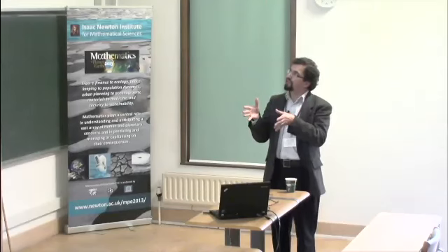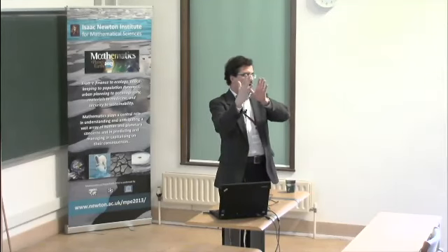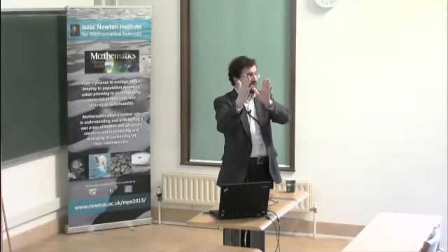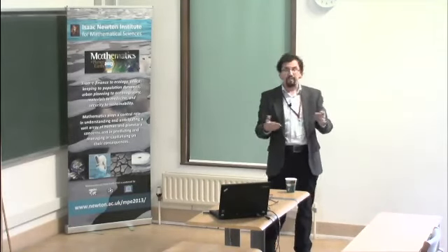So I would like just to say that nowadays there is some interest to explore the droplets of liquid crystals from the point of view of using them as topological tests of the existence of new phases with background nematic type. One of those new phases is the so-called biaxial nematic phase. So you can imagine molecules not being just rod-like or disc-like. You can imagine them being box-like. And if you deal with boxes, then not only the long axis of boxes can align, but also the short axis of boxes can align parallel to each other. And that would be a biaxial nematic phase.